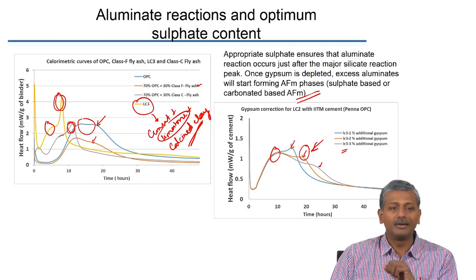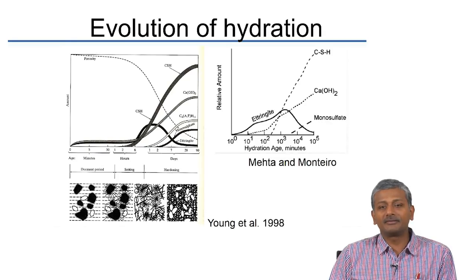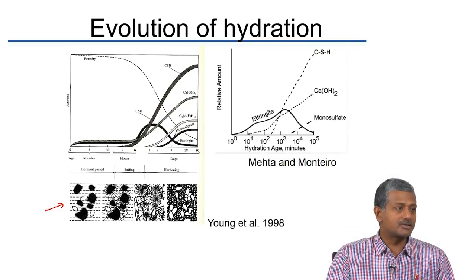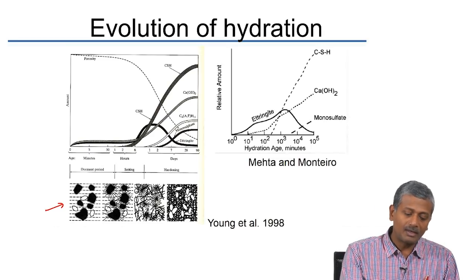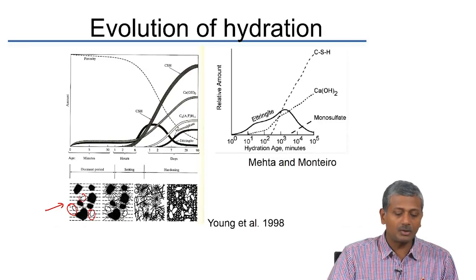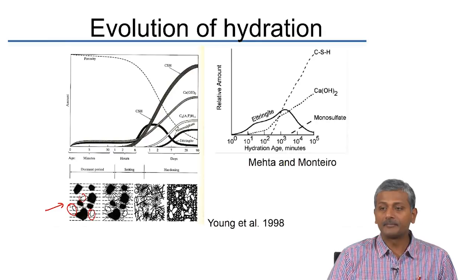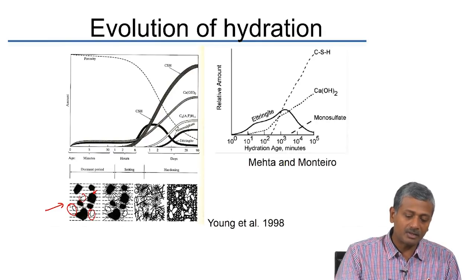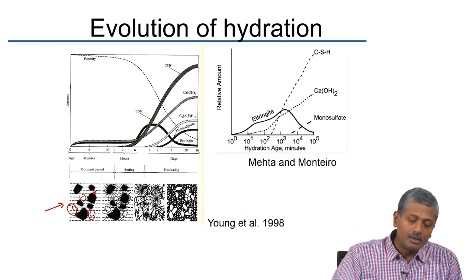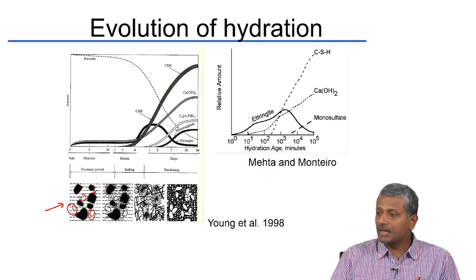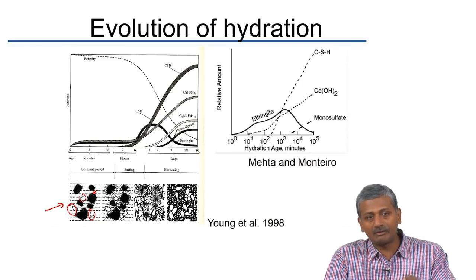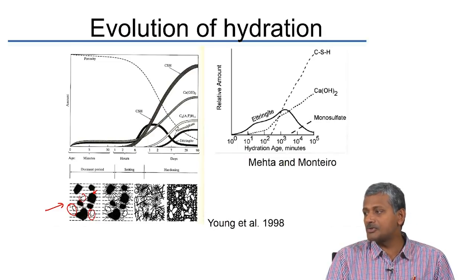Looking at how cement paste actually evolves: starting from cement particles in water, during the dormant period you can see well-formed crystals already present. Needle-like substances on cement particles represent the barrier layer of hydrates. Some well-defined crystalline calcium hydroxide forms away from the cement particles due to calcium ions dissolving out. During this dormant period, the reaction proceeds at a very slow rate.